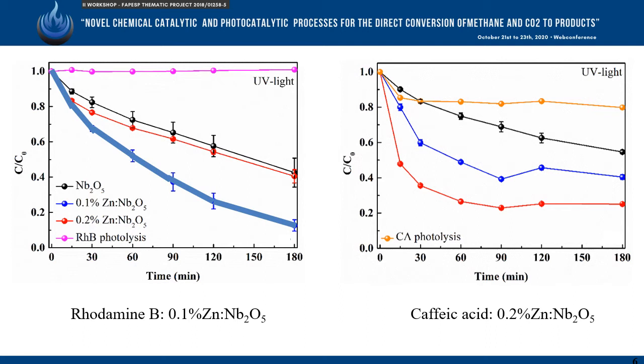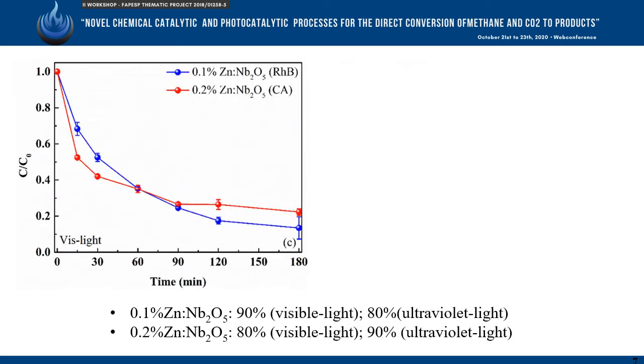On the other hand, the best photocatalyst for the degradation of caffeic acid was the sample containing 0.2% of zinc, degrading about 90% of this pollutant, also under ultraviolet radiation. It was proved theoretically and experimentally that the doped samples presented band gap energy below 3 electronvolts, therefore they could be activated under visible light. In this sense, it was observed that under visible radiation, the samples degraded almost the same amounts of rhodamine B and caffeic acid as the values obtained under ultraviolet light.